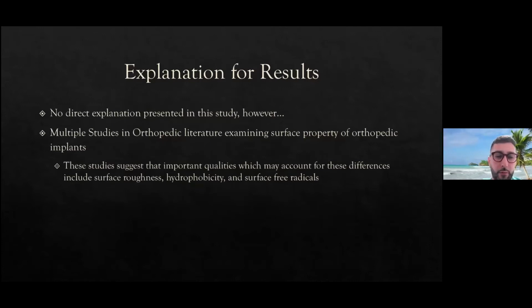But they do reference multiple orthopedic studies that talk about this, and they basically state that there's a number of factors that are important to consider in terms of propensity for biofilm formation, including surface roughness, hydrophobicity, and surface free radicals. So certainly, and I didn't find any studies on this specifically, but you can imagine, again, talking about texture of implant, that would influence biofilm formation.